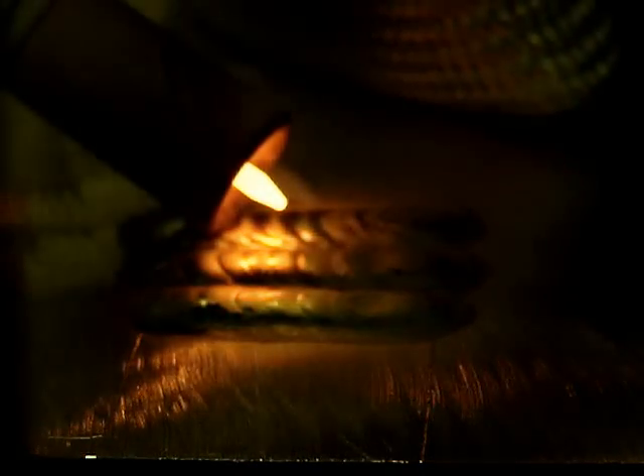Alright, from the ceriated we went to the 1.5% lanthanated. Did a little bit better, but we still got a little uneven ball on the end that melted a little bit more than I would have liked to have seen it. Next, 2% lanthanated. Now this is more like it. 200 amps. Start off with a sharp electrode, barely melted the tip, and it balled evenly. That carried amperage a whole lot better than the first two.